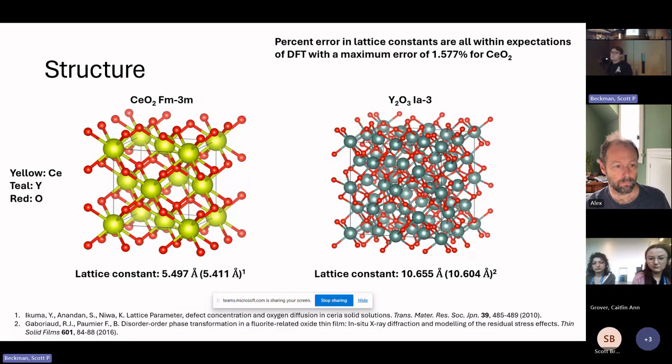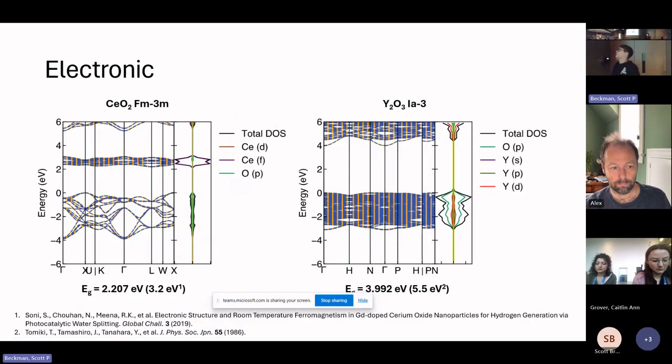We also looked at the electronic properties of these pure crystals. I know many of the experimentalists, if we look down here comparing the DFT band gaps with the experimental band gaps, they're significantly lower, but that's to be expected within DFT. These are values that are comparable to what has been seen in the literature, calculated within the literature.